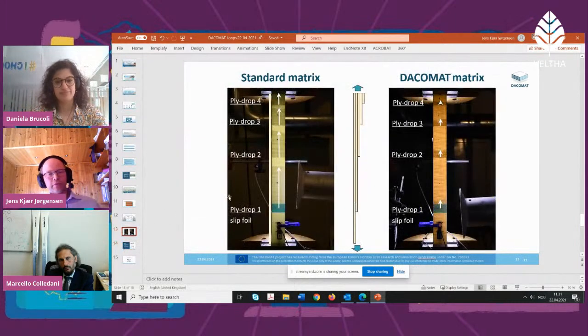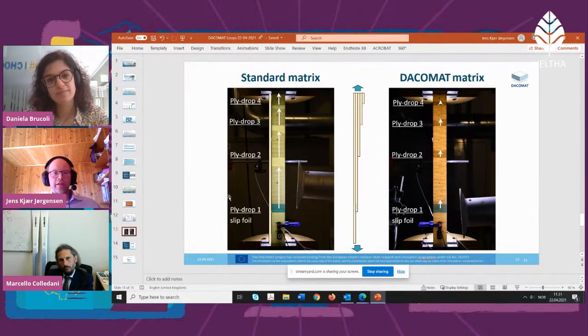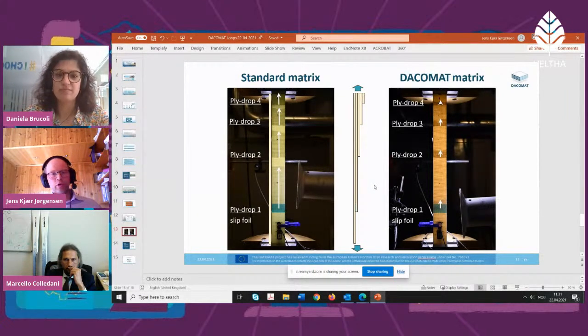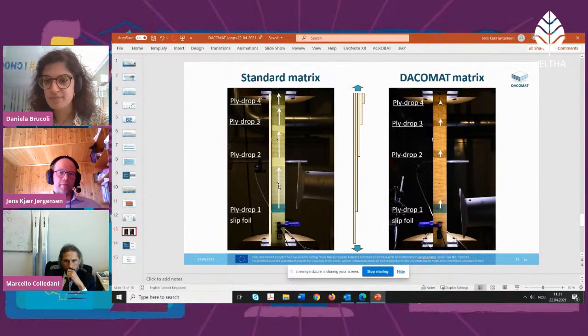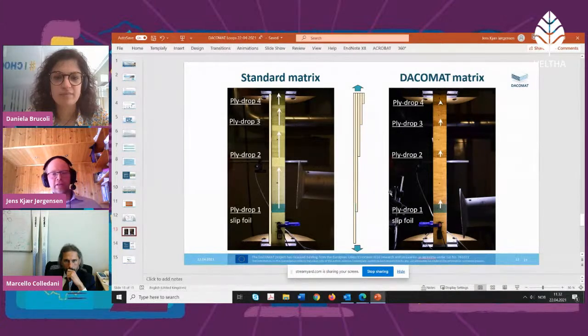As one of the results from the project, we made materials, resins and fibers with improved properties toward this behavior. And for now, we made, as a first-generation small-scale demonstrator, a composite with ply drops, one with standard materials and one with DACOMAT materials. And we subjected them to the same load for a certain number of cycles. And here the arrows indicate the length of the crack growth during a certain number of cycles, which is substantially lower for the newly developed material than for the reference material.